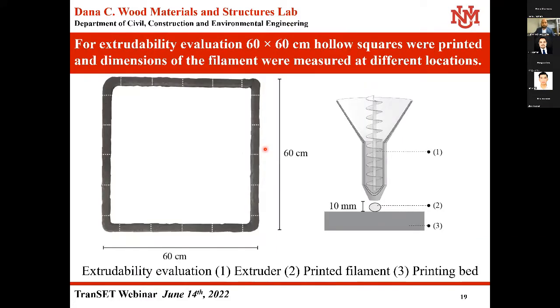For the extrudability evaluation, we printed a hollow square of 60 by 60 centimeter dimensions, and the dimension was measured over the filament at 5 different locations to see the dimension consistency and conformity over the length of the filament.